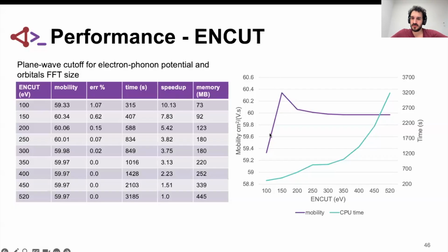In this plot on the right, I show the value of the mobility, with the axis on the left and the computational time on the right. As you increase the cutoff, the computational time naturally just increases. But at some point, increasing the cutoff doesn't change your final value. The optimal region for this particular case is actually 150 EV, which is even below the ENMAX that you would find in the POTCAR. You are still below 1% error, and you can run 7 times faster. So this is very important.